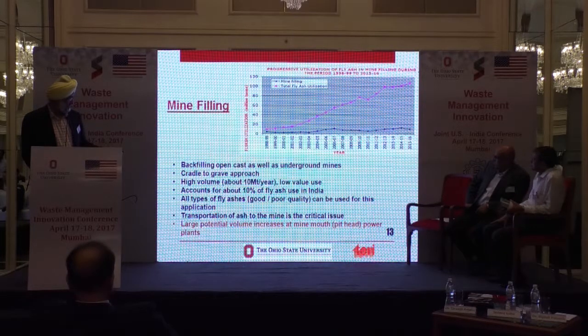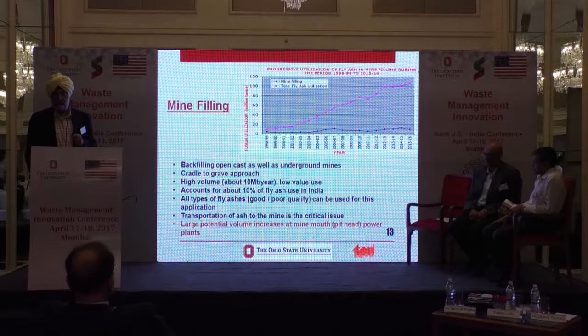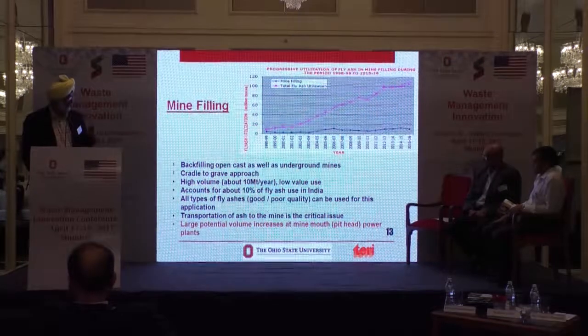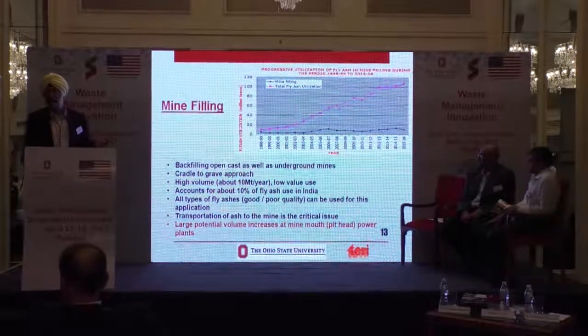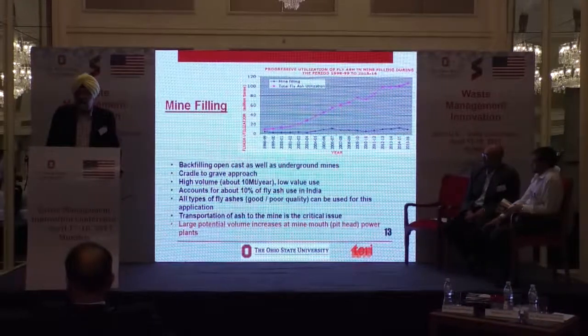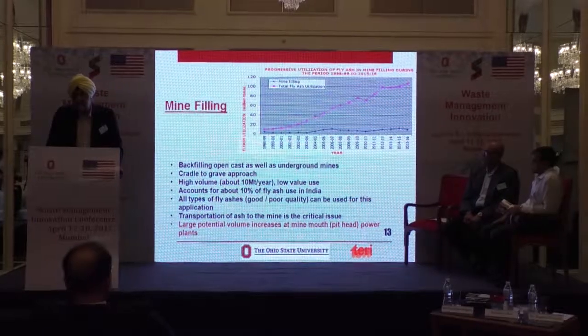And about 10% of all fly ash use currently is here. The advantage here is you can use both low and high carbon fly ash, what I call good and poor quality from a concrete perspective, can be utilized in these applications. And the place where this has the most amount of potential is at what we would call pit head plants here in India, or mine mouth operations. In fact, in the US, in mine mouth operations, this is the standard practice today.